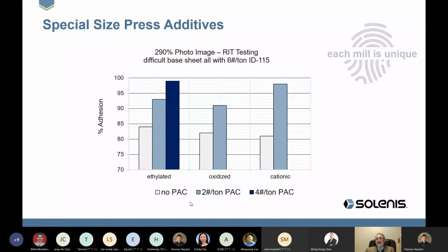But as I mentioned earlier, there are some mills that are maybe more unique than others, maybe more of a problem than others. And so I came out with a second generation product in which I added aluminum salts along with our material. The best working one was polyaluminum chloride, or PAC, we call it. And what we found is we add this material along with our additive, and we took paper that was passing the qualifications. Again, this was a very difficult base sheet with the most difficult image and a 10-minute test.